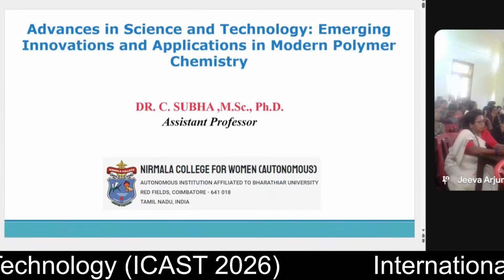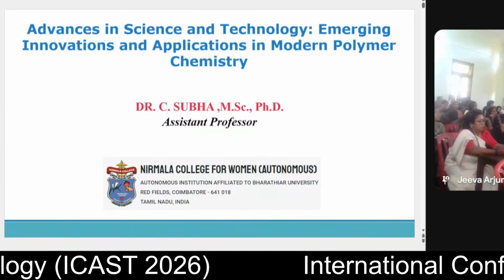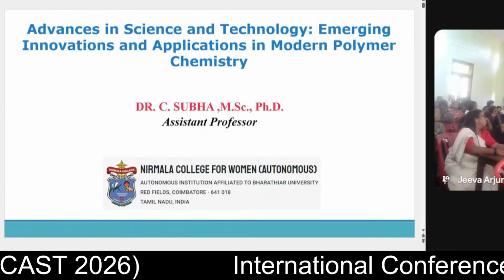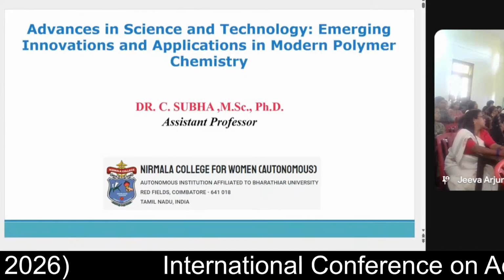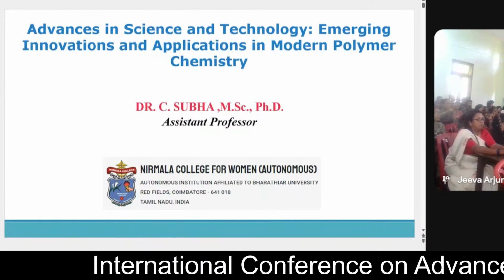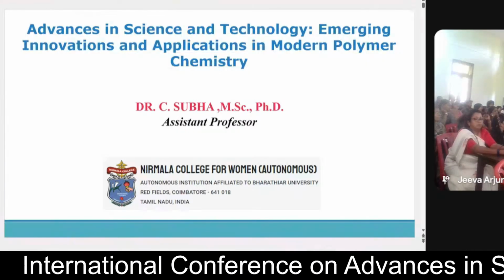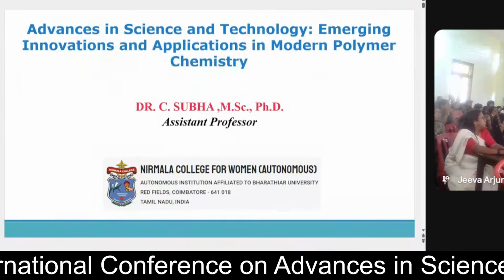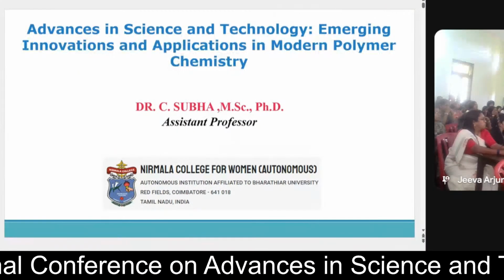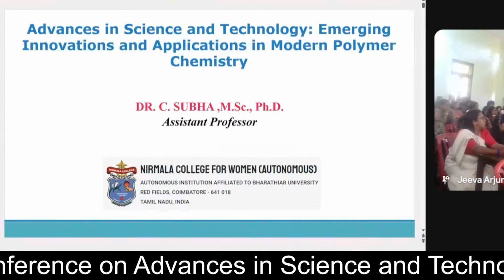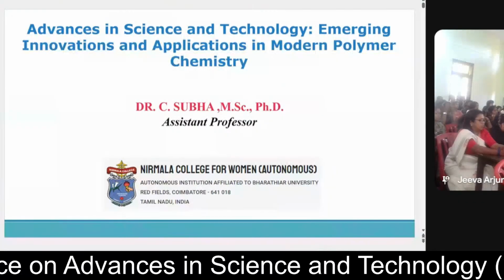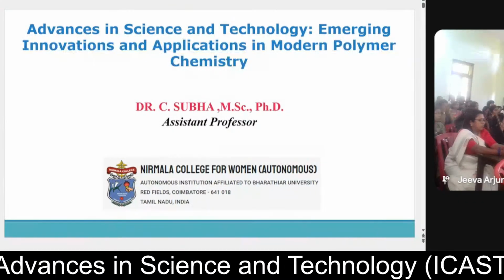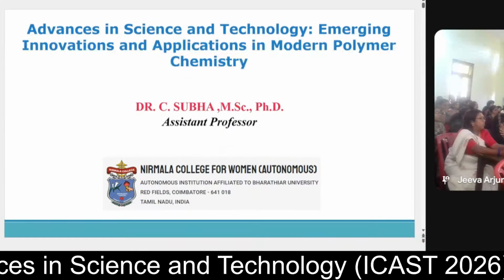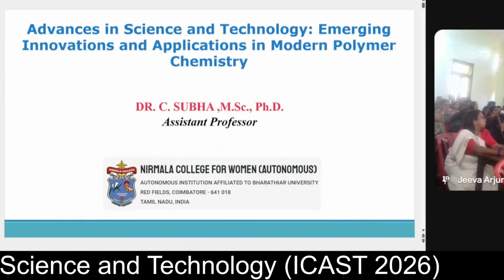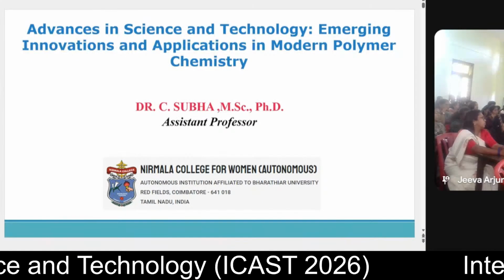So you look at this data, and P1 and P5 were able to get a high crystalline nature, and the others show an amorphous nature. The crystallinity may be due to the presence of heteroatoms or those things present in the polymer backbone. Okay, so now we have synthesized the polymer, and now we have characterized it.